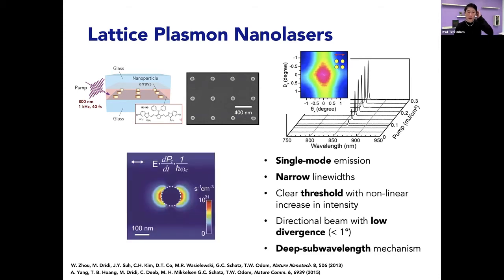And one feature that I really appreciate about this system is that the mechanism is a deep subwavelength one, meaning this is a spatial map of the stimulated emission rate term. And so you can see that only molecules that are within the vicinity of the hotspots contribute to population inversion.